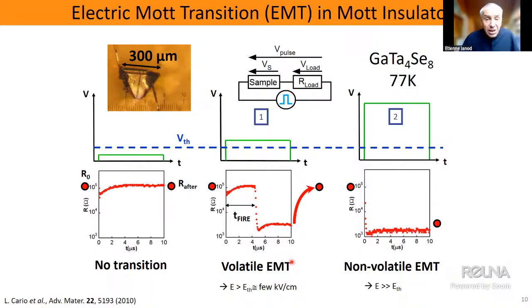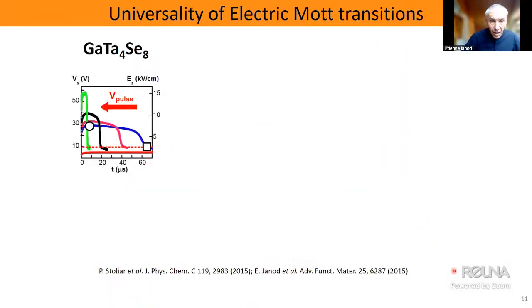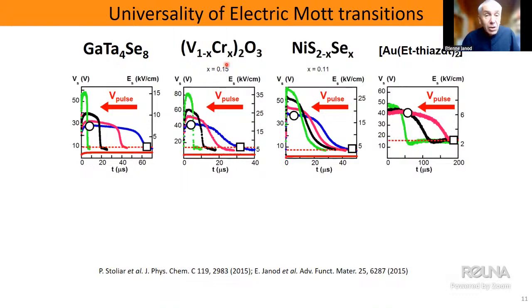But if we continue our game and further increase the value of the electric pulse, we obtain the same transition. It occurs here in the very beginning of the pulse, and then the resistance stays low during the pulse. But after the pulse, the resistance remains in its low resistance state. We call that a non-volatile electric Mott transition. And what we have discovered is that this property is not specific to one Mott insulator, though it's GaTa4Se8 that I showed you on the slide before, but it also occurs in all the Mott insulators we have tried.